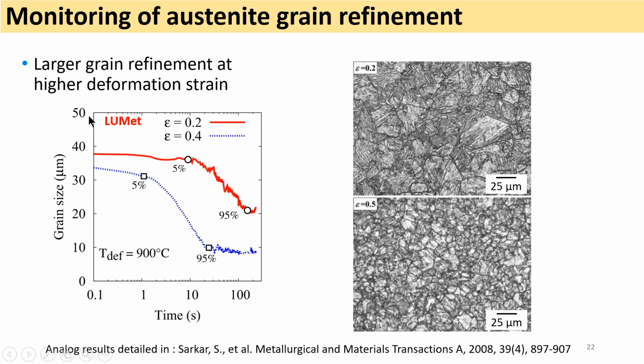So what you can see here in this figure is the grain size varying with time during this recrystallization process. The red curve corresponds to the strain of 20% and the blue curve to 40% strain. What you can see is that as we increase the strain, the onset of recrystallization occurs much earlier, corresponding to this sharp decrease in grain size, what's called grain refinement during recrystallization. And so here, Lumet was able to capture this recrystallization occurring after the deformation. You can access similar results in these studies, which were done in 2008, where all the setup and techniques are described in detail.